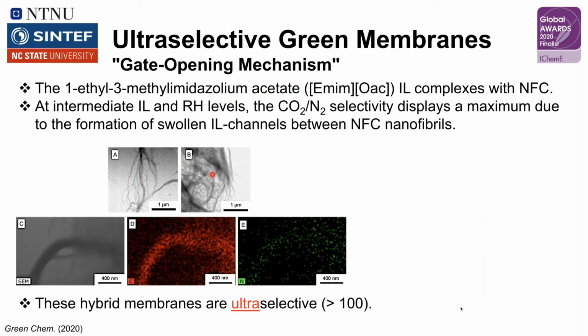This shows what the nanofibrils look like when they are put in contact with the ionic liquid, which is 1-ethyl-3-methyl-imidazolium acetate. And then we can look at some STEM images that show, once again, we have the nanofibril, that's the real space image. This is an energy dispersive spectroscopy image that tells us that, yes, as expected, the nanofibril is composed of carbon. And the last one is a nitrogen map that corresponds to our ionic liquid, and that too is corresponding to the nanofibrils. So this provides direct evidence that the ionic liquid does have affinity for those nanofibrils.